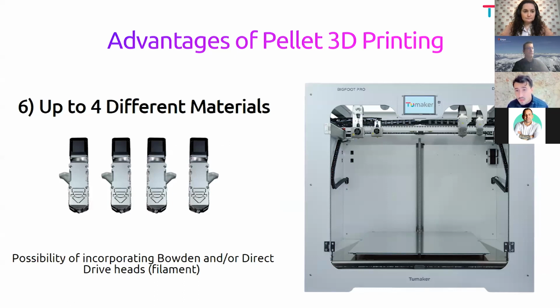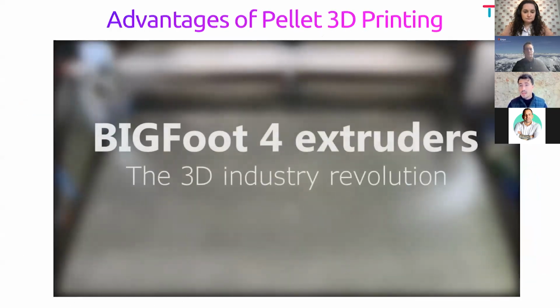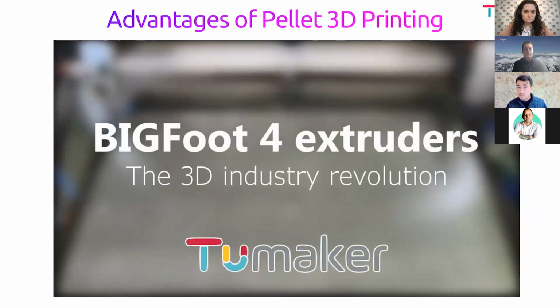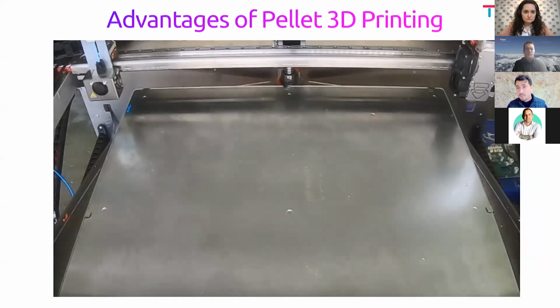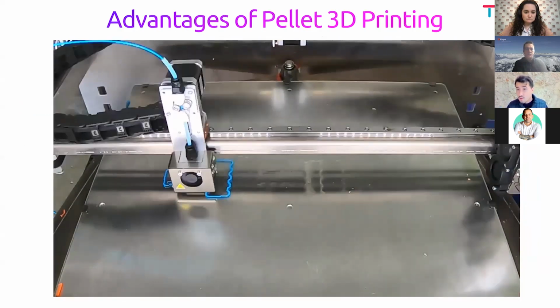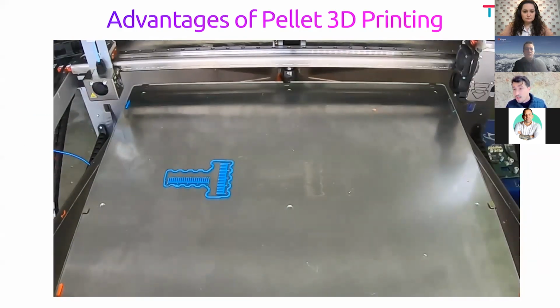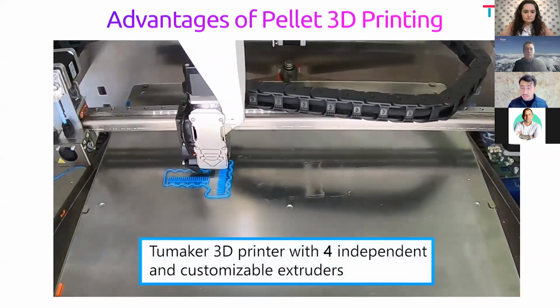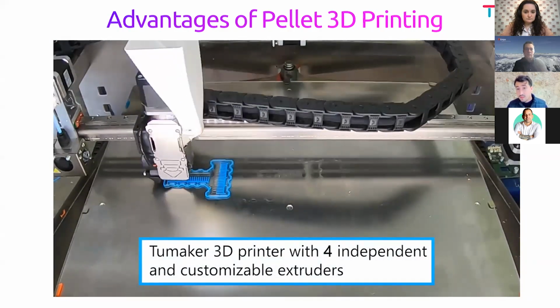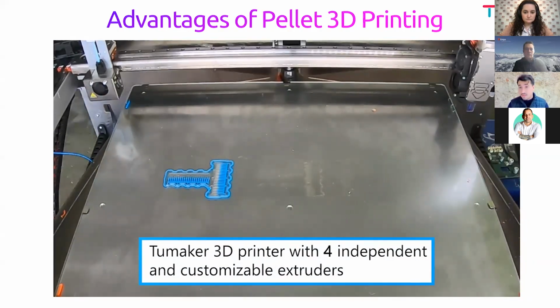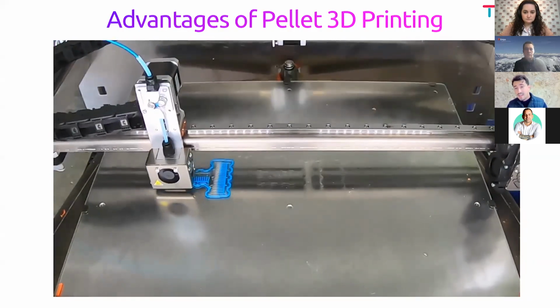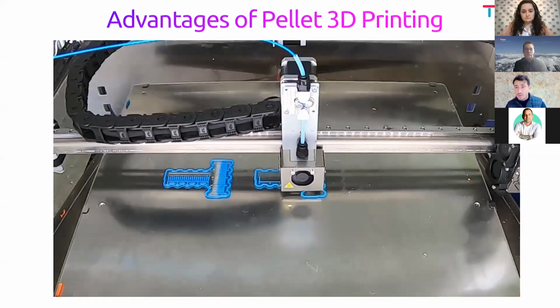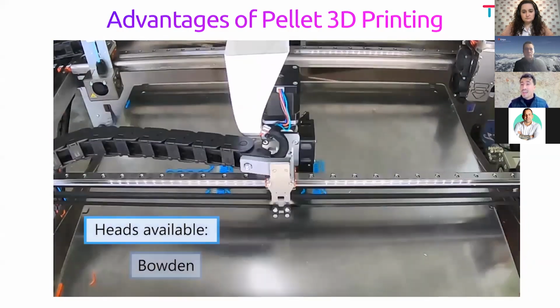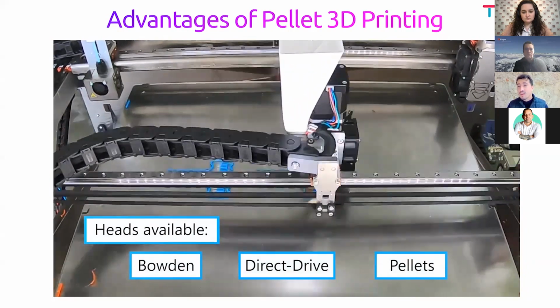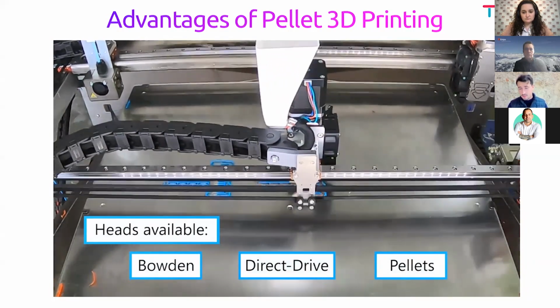In the next video, we are going to see one of our machines working. This one contains 4 extruders, 2 of them are pellet and 2 of them are filament. So the first one is going to print the outer part of that structure using filament 3D printing. Then that same structure is going to be filled using a pellet extruder with a different polymer at a different temperature. Then again, the same head is going to print a second structure, the outer part, and another pellet extruder is going to deposit a different material compared to the other one.